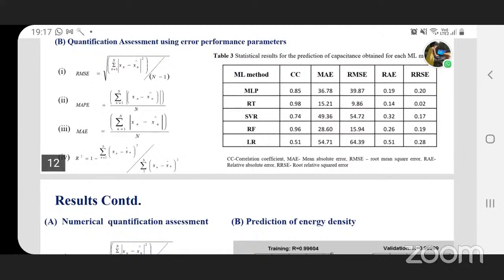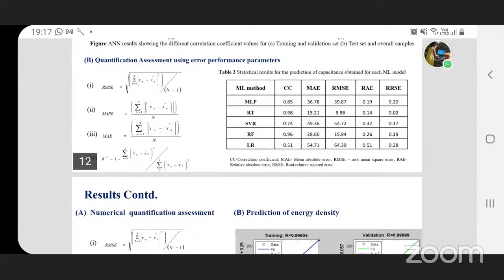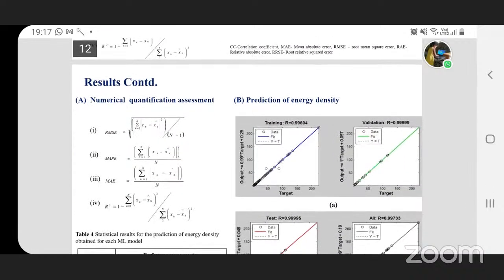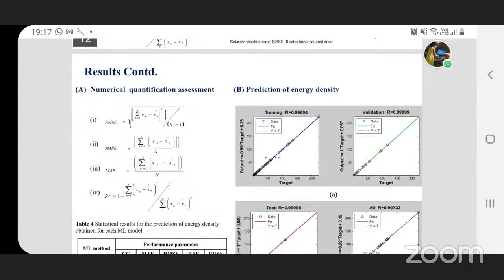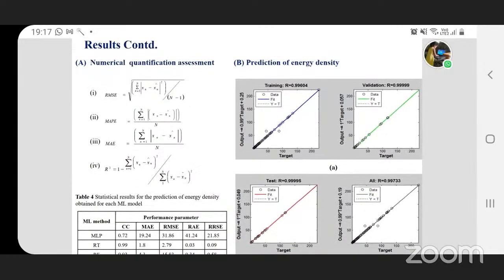So the 5 performance parameters that we considered were correlation coefficient, mean absolute error, root mean square error, relative absolute error, and root relative square error. Table 3 tabulates the values of these error performance parameters based on the different ML methods. From table 3, we can see that random tree and random forest are having the maximum correlation coefficient, whereas the root mean square values for these two methods were relatively low. Hence, they were able to predict the capacitances very easily, or we can say more accurately as compared to the rest of the methods. After getting the prediction of capacitance, we move to the prediction of energy density.